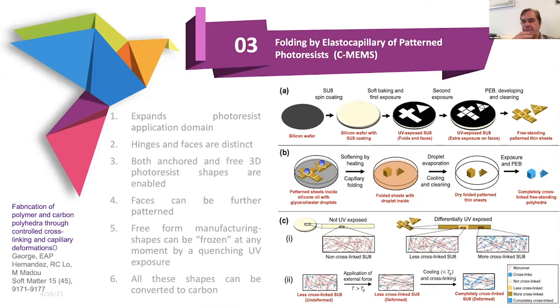self-assembling structures. Here is a slide I will spend quite some time on because this is kind of the secret sauce. It shows how we can, by using elastocapillary of patterned photoresist, make pretty much any shape we so desire. First of all, we have a wafer of silicon. It can actually be any flat substrate. We coat that wafer with SU8, a photoresist. We do soft bake and first exposure. And what we make here, as you can see, are the same shapes George et al. was making, namely a pyramid, this one, and then this cross structure.